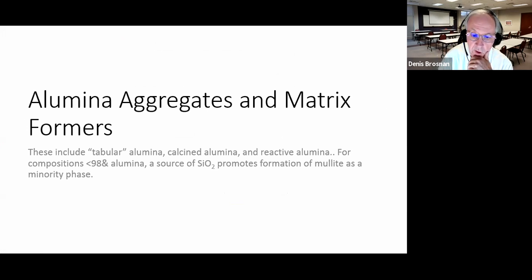Now, we're going to talk today about tabular aluminas. Tabular aluminas are so named because the crystals of corundum, the individual crystals, are tablet shaped in nature. These are really high fired products. So they're very stable aggregates at elevated temperature, meaning they don't shrink much when you heat them to a very high temperature after you've made your product. We're also going to talk about calcined aluminas, not much about reactive aluminas, but calcined aluminas are fired at lower temperatures, low enough temperatures only to form aluminum oxide, but to leave them more reactive so that they will sinter more readily. And so these compositions are generally about 98% plus aluminum oxide, a little bit of silica. They're also characterized by their soda content, their sodium oxide content.